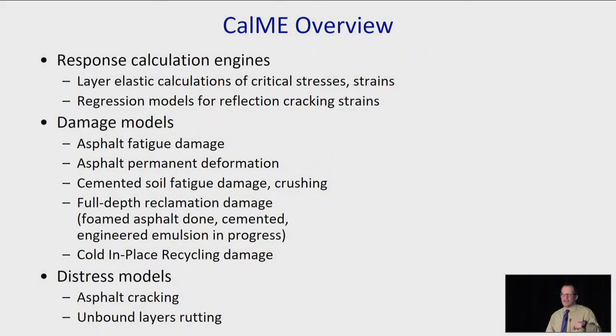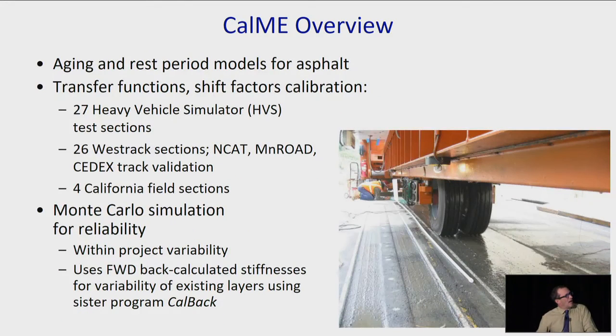The distress models, then: we simulate what's happening with the damage, and then we calibrate the damage to the asphalt cracking and the unbound layers rutting. So aging and rest period models are included for the asphalt. We knew historically from the Shell method that shift factor can vary greatly depending on the rest periods between the traffic. We wanted to account for that. It's not well calibrated yet, but we do have a model that accounts to some degree for that.